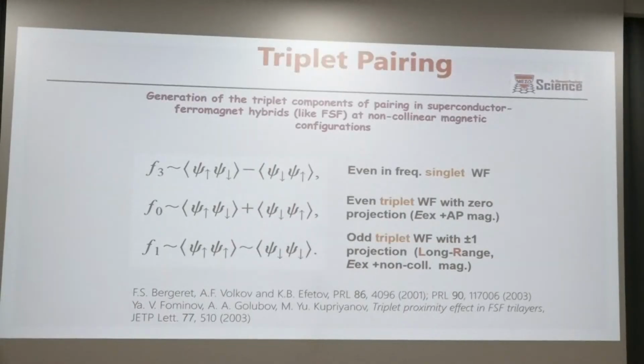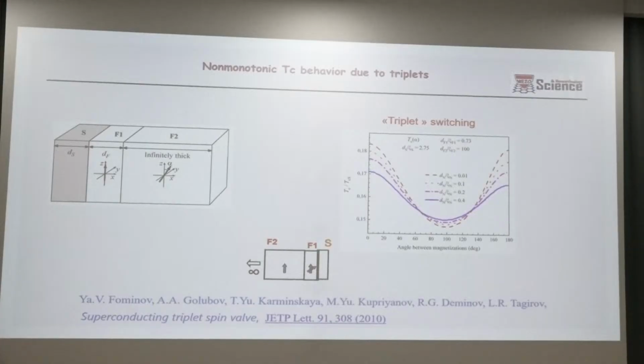But the operating field for changing the magnetization is still several hundred oersteds. That's why this element can work like an artificial neuron, but we need an even smaller magnetic field for operating. And for this purpose, another idea can be used, so-called triplet superconductivity. If the magnetization is not changed to the opposite but just inclined, for this purpose only a few oersteds are necessary. Then the critical temperature can change like in the theoretical curve on the right panel.